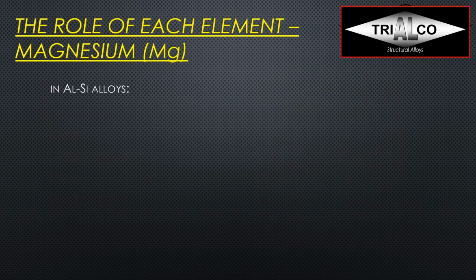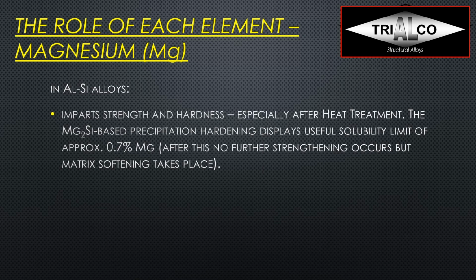In aluminum silicon alloys, magnesium is used for strength and hardness, especially after heat treatment. It actually gives us the heat treatment response in the alloy. If I have aluminum and silicon as a binary alloy, I will not really get a heat treatment response. So the Mg2Si, or magnesium silicide based precipitation hardening, displays a useful solubility limit of approximately 0.7% magnesium. After that, it doesn't really do anything anymore. It actually softens the matrix. So that's why usually we see most alloys specified up to 0.6% magnesium.